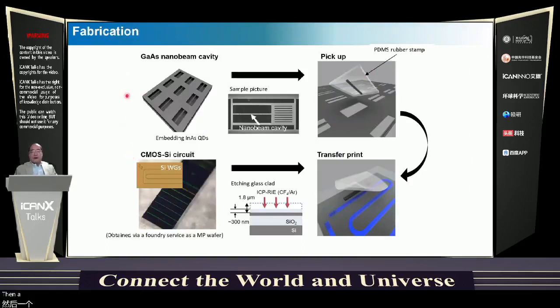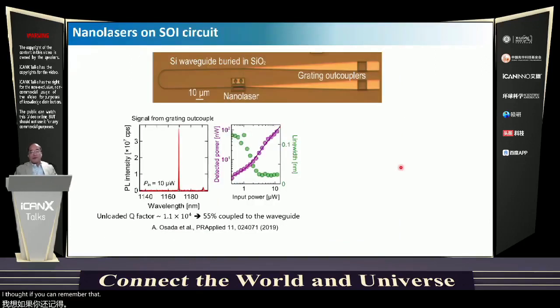Then we fabricated gallium arsenide nanobeam cavities, and this is the pattern formed on the wafers, and this was picked up by PDMS rubber stamps. And in parallel, we prepared the CMOS silicon structure. This was fabricated by the foundries. And then the laser structure is transfer printed on the silicon substrate. Sorry, silicon waveguide.